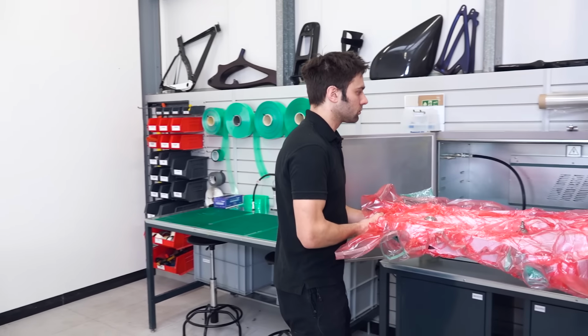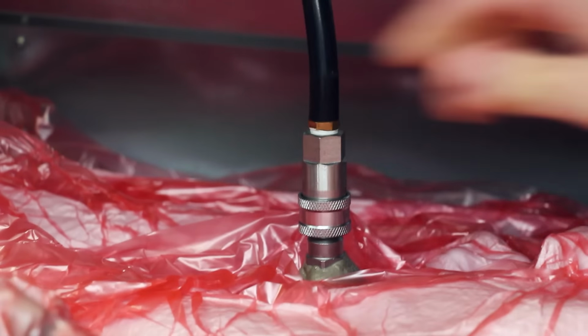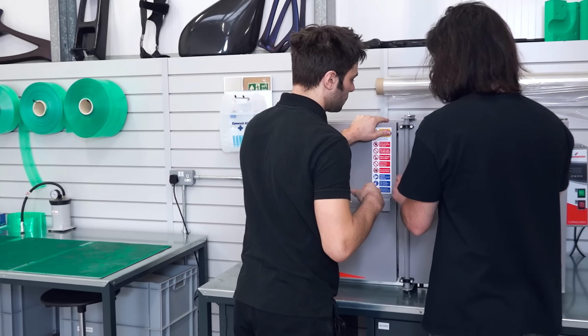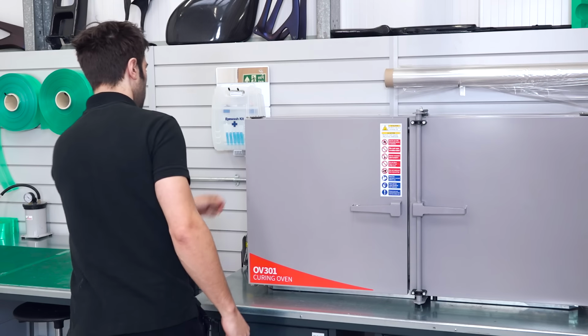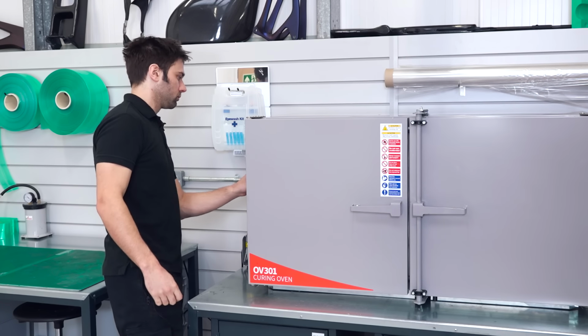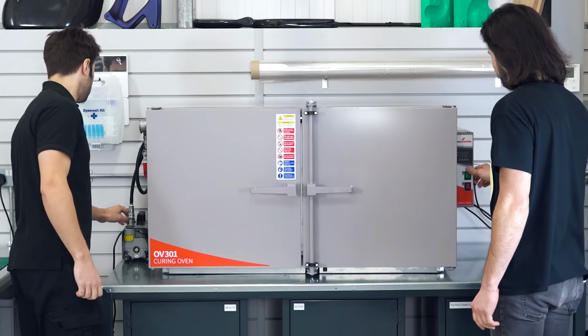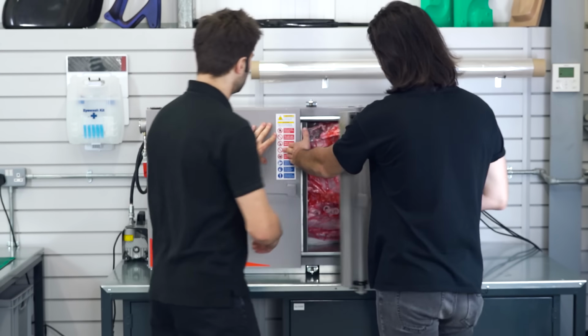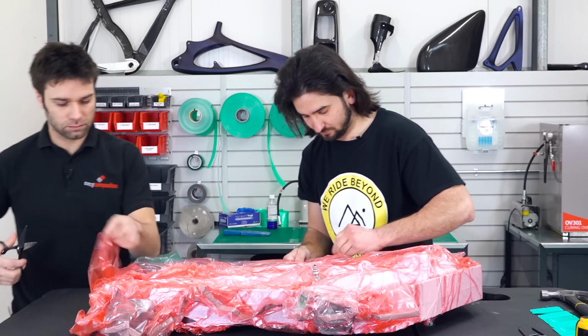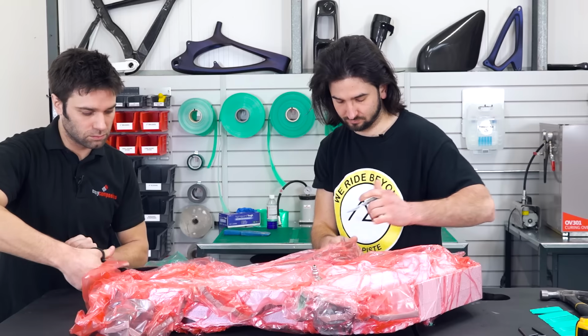For this cure, we're using the XPreg XC110 extended cure cycle, which is a two-step cure cycle with a final cure temperature of 120 degrees C. Full details of the recommended cure cycles can be found on the XPreg XC110 technical and processing datasheets on the Easy Composites website.